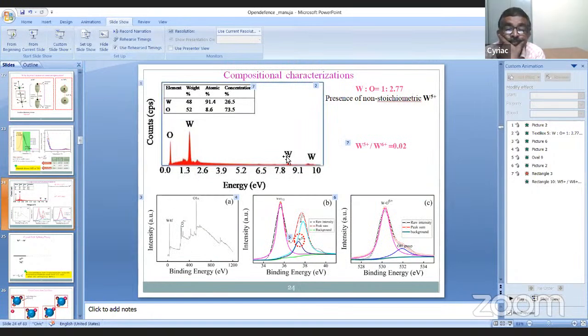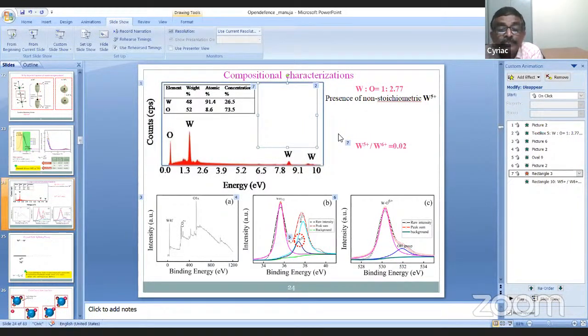Is the slide clear, sir? Yes. From this EDAX and XPS measurement, we identified the presence of W5 plus, and also we deconvoluted the XPS spectra of the sample. I agree, Manija, but from EDAX, how will you identify it? That's my question. From the EDAX, we get different weight and atomic percentage and concentration of the sample, tungsten and oxygen. Different weight percentage and atomic percentage are available from EDAX spectra. Then by calculating the ratio, we can identify the presence of non-stoichiometry, and the presence of non-stoichiometry identifies the W5 plus state in the material.